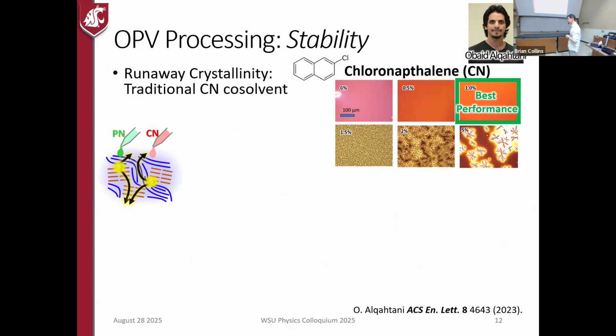This is a co-solvent. So typically you dissolve these molecules into an ink. It's got a solvent. In this case, it's chloroform. It's very volatile. It just goes away really fast as soon as you print it. So you add in a low volatility co-solvent so that you have this wet film that can order and organize and phase separate.